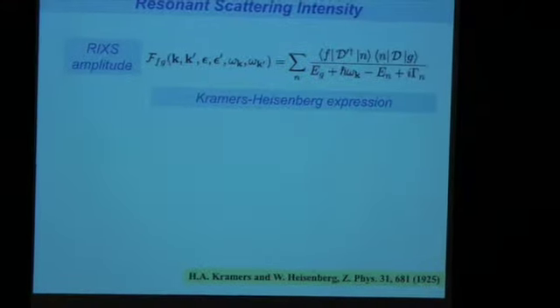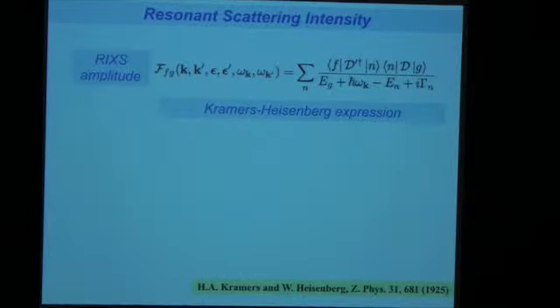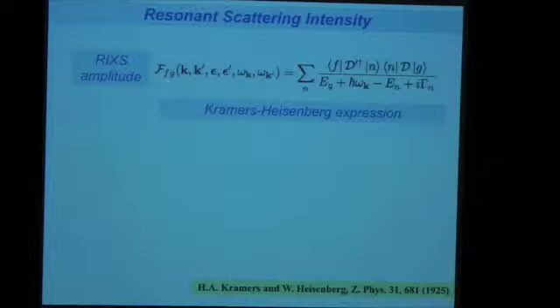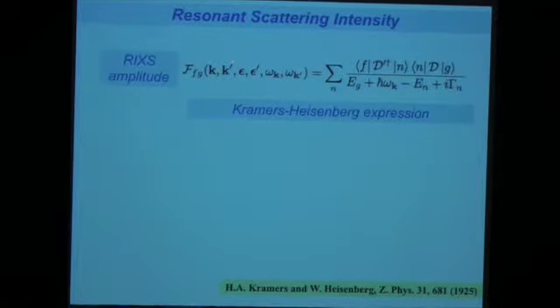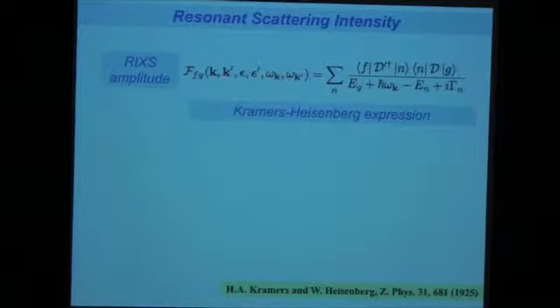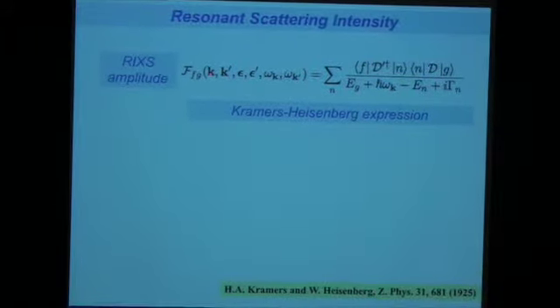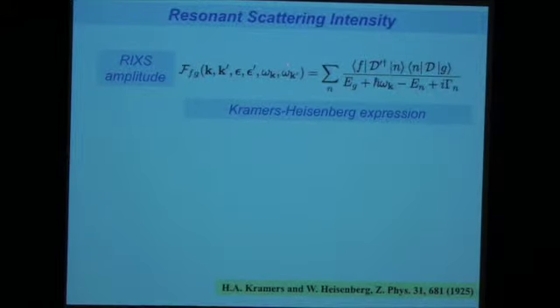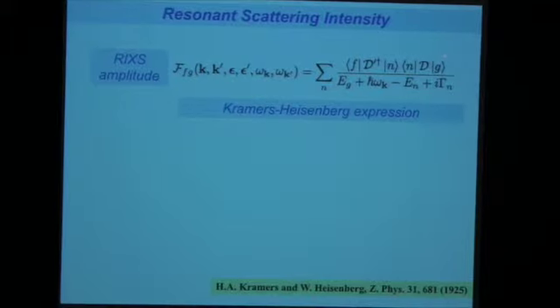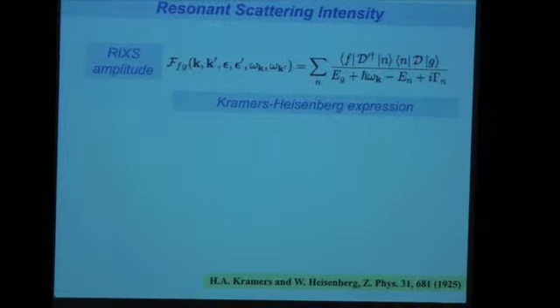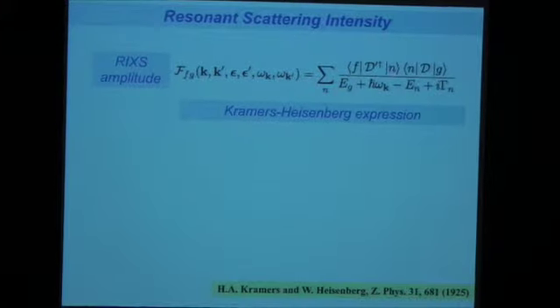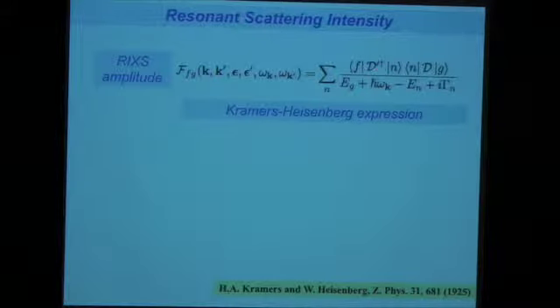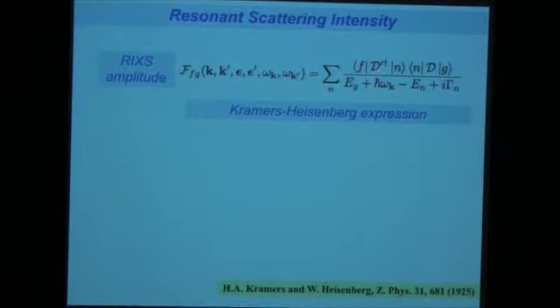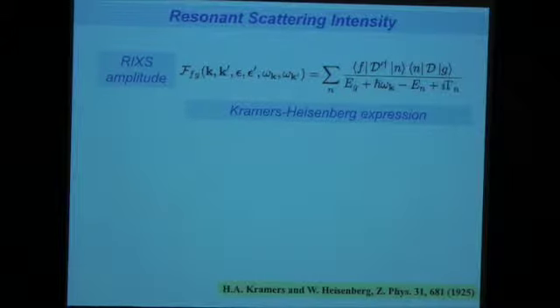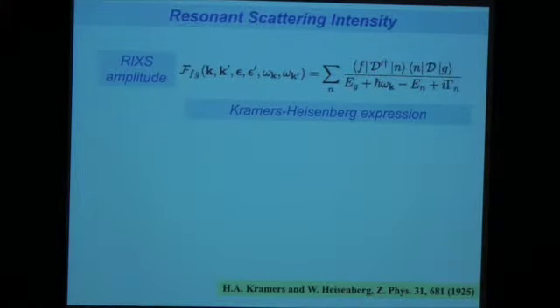So this is now, in principle, a good thing. So how does it now work in terms of some scattering formulas? It's a second order scattering process. So the RIXS amplitude is given here, and it depends on the momentum of the incoming photon, the momentum of the outgoing photon, the polarizations of incoming and outgoing photon, and the energies of incoming and outgoing photon. The following way: you start with the ground state, you act with the absorption operator, you get into an intermediate state. From this intermediate state, you act again with the absorption operator, or its conjugate, you emit a photon, you end up in the final state, and because it's a resonant process, you divide by the denominator, which contains the intermediate state energy.